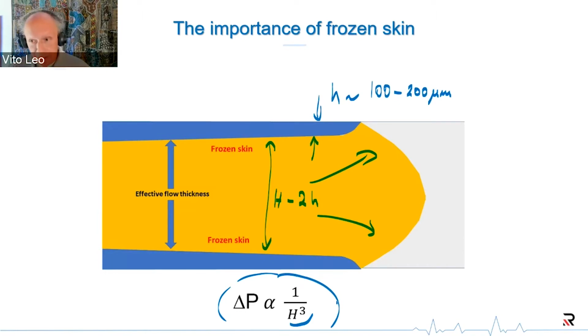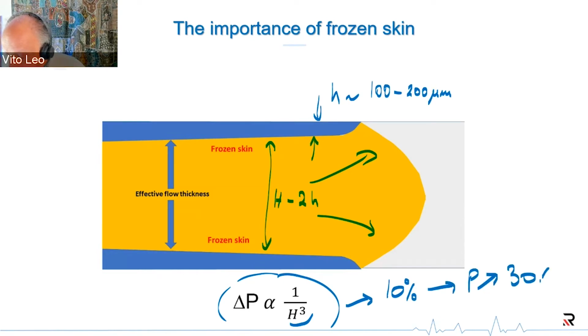If we linearize this and think in terms of percentage, from this formula we can say that if 10% of the channel is blocked by the frozen skin, that will give you a pressure increase of about 30%. That's because of the cube. So it's just a linear approach of this complex formula. Every time you lose 10% of effective thickness, you need to add 30% more pressure. So you see it's a very, very strong effect.